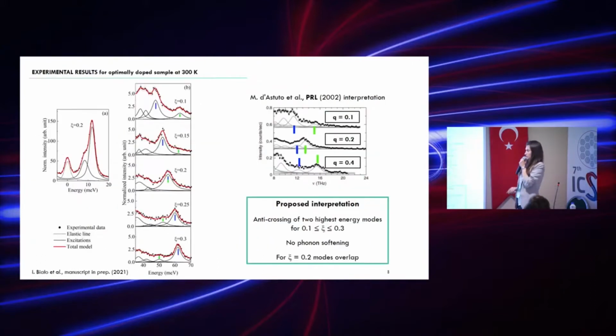And that's an example of our results. Results for optimally doped sample at 300 K. This part is a part of acoustic phonon modes, and the middle panel is for optical phonon modes. And here we also have the green and the blue mode. The green mode is shifting in energy towards lower energies, while the blue mode is shifting to higher energies, going